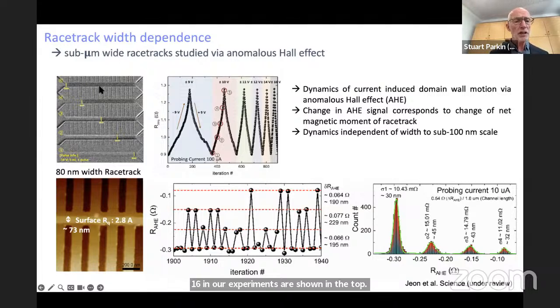What we do now, the top left shows you optical images as we move a single domain wall through the racetrack, and in the top middle you can see the anomalous Hall signal as we apply the current pulses. The iteration number is the number of current pulses that we apply, and on the top you can see the voltage changes from +9 all the way to +16 volts, so that the intensity of the current we're passing into the racetrack significantly increases, and that means you need a smaller number of current pulses to move a single domain wall from the left to the right of the racetrack.